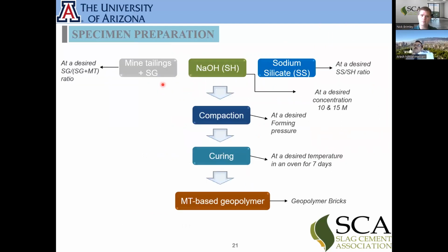To prepare the specimens, we followed this procedure, very simple. So we mix the mine tailing with the slag at a desirable ratio. The reason we use the slag, we are going to talk about it later, but the amount of the slag we use, we try to use it as minimum because the slag is kind of like an improvement for us in this study. The slag helps us to produce better and durable material.